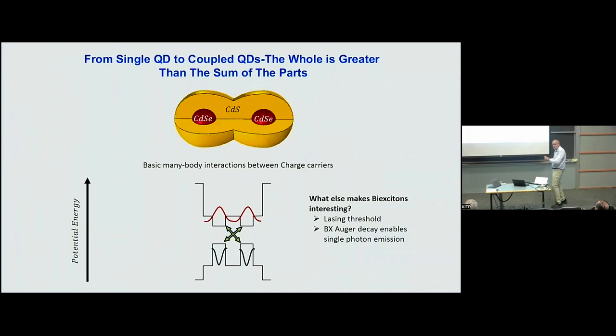And also, on the other hand, in the monomer it will quench because of increased non-radiative Auger interaction with all these charges in the same volume. And that's not so good for lasing maybe, but it's quite good because it enables thinking about monomers as single photon emitters, because 2-photon emission is quenched due to Auger interaction.